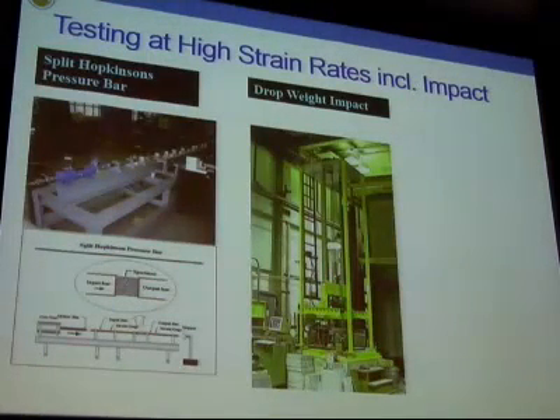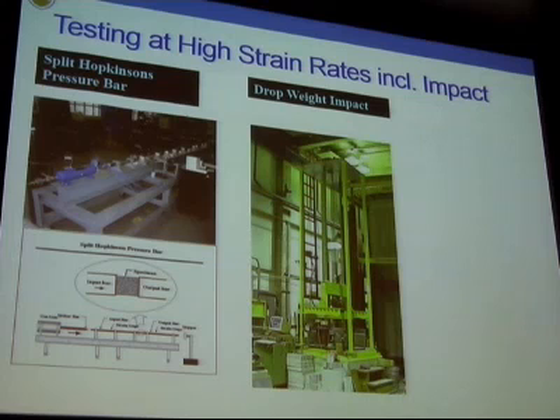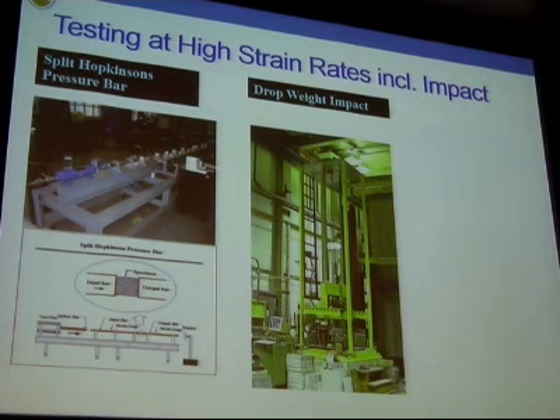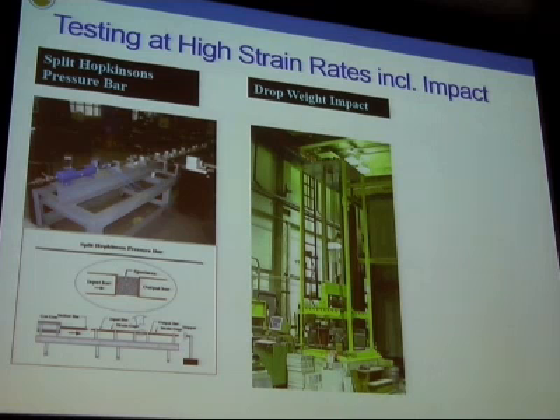So how do we understand how these materials, or fiber-reinforced concrete, behave under high rates of loading? There are several methods available. There's the split Hopkinson pressure bar. This is actually from Tongji University, where I have some joint collaborative work looking at how these materials perform under high rates of loading. And this is a machine we have here at the University of British Columbia. It's a drop tower whereby you can generate very high rates of loading and see how those EDCCs that I'm talking about would perform under high rates of loading.